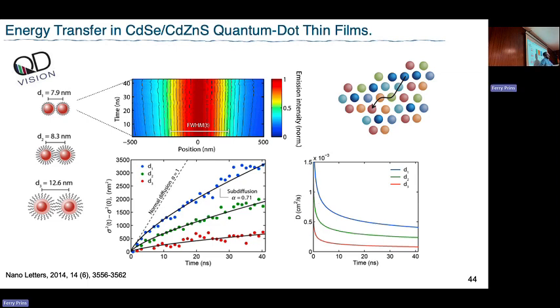So you can imagine that if you're diffusing in a disordered energy landscape, you are populating more and more lower energy sites, which have less and less possible escape pathways. So at the end of the day, the diffusion slows down.